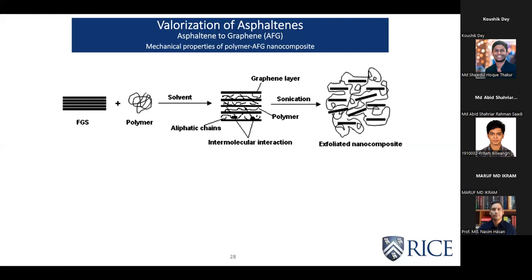So, like I said, the turbostratic nature was very important, because our idea was to show the funding agencies that we can convert the asphaltenes into graphene, and then we can use the graphene in different applications. So for showing the applications, we developed these polymer and AFG, asphaltene flash graphene, nanocomposites. And because of the turbostratic nature, we speculate that we could easily get very well exfoliated and dispersed graphene sheets inside the polymer matrix. For forming good polymer composites, it's very necessary to exfoliate these nano reinforcements and then disperse them well. So I guess the turbostratic nature helped us achieve exfoliated nanocomposites.